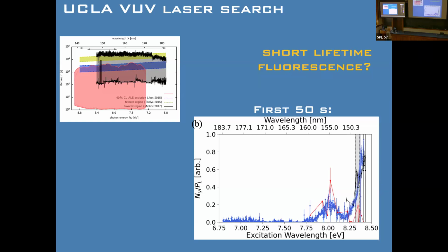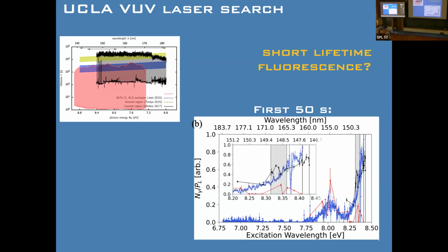As we kept going though, around 8.3 eV, the fluorescence really started to go up and up. Let me zoom in here. With the current laser system, we could only go down to about 147 nanometers or so. That's shown in blue. You see in the 232 doped crystal, there really wasn't anything there. We took out another crystal that had 229 in it, and we also saw, shown in black, this sort of transition.